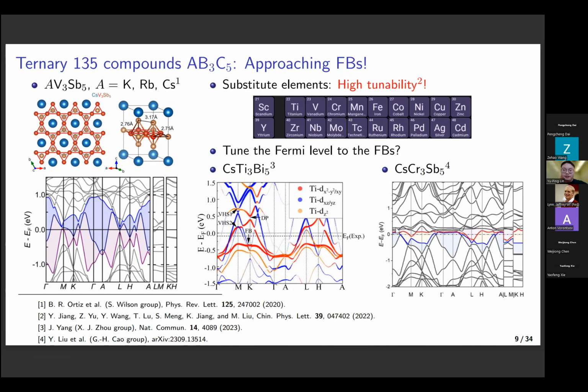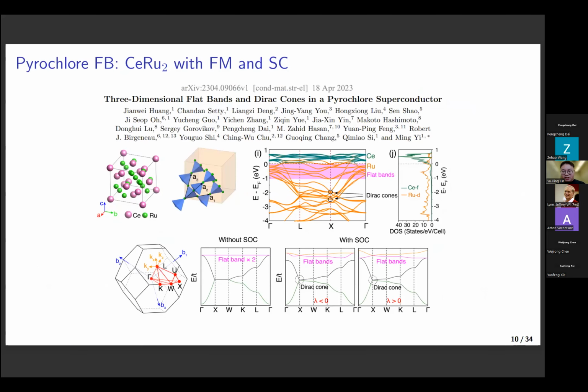So if we can tune the elements of the ternary compounds, maybe at some moment we can find materials where the Fermi level is really in the flat band, so that we can see what interacting phases they have. And in addition to the kagome metals, more recently, it has been shown by the Rice experimental group again, for example Pengcheng and Mingyi, that the cerium diruthenide actually also holds a flatband close to the Fermi level. One interesting thing about this compound is that in addition to the ferromagnetism below 40 Kelvin, there is also superconductivity below 6 Kelvin. So this is one of the promising examples where we can find flatband superconductivity.